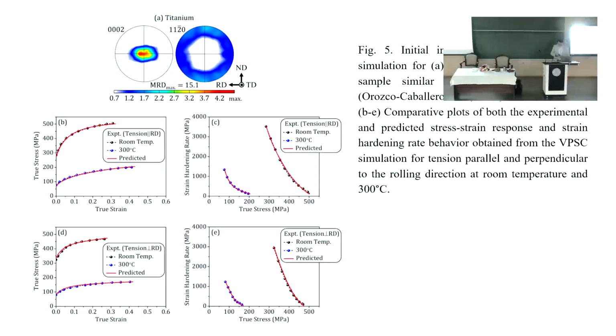That's the case for titanium. Titanium sheet can be very anisotropic. You see here, like usually the so-called basal poles are normal to the sheet of the titanium sheet. And even with this extremely high anisotropy, one can conveniently reproduce the results. That's for titanium, at different temperatures and different loading directions within the plate.